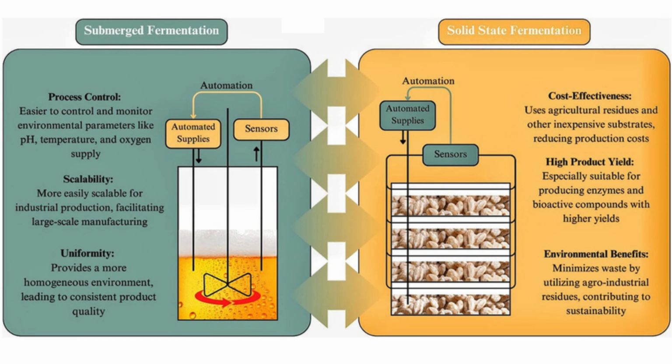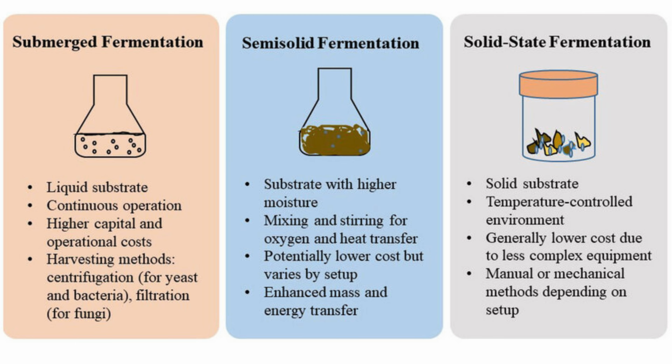It is believed that the cultivation of fungal biomass under submerged conditions will result in the production of slurry or pelletized biomass that would demand laborious processing before a coherent piece of material can be obtained. Expectedly, the material obtained under SMF has been noted to possess different tactile properties in comparison to fungal leather substitutes during SSF, which have a more spongy morphology. For instance, in a study aimed at producing engineered living materials from G. lucidum, cell pellets produced from SMF were blended, homogenized, and plasticized to finally form a flat, leather-like material. Such processing was also carried out successfully in the production of fungal materials with leather-like properties under submerged conditions using bread waste as the substrate.